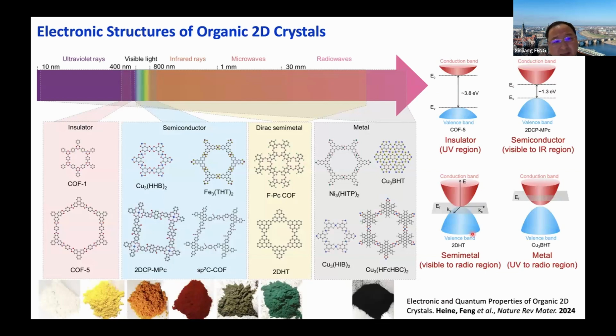In organic 2D crystals, you can find a broader range of materials, ranging from the insulators with a large band gap to the semiconductors with a well-defined band gap, Dirac semimetals, and to metallic materials, which are highly conductive zero-gap materials. So basically, you can find almost all these materials in the organic 2D crystals. It's possible to make the insulator, for example copper-based materials, with low electronic building blocks and large band gap. But it is also possible to have semiconductor materials, with the beautiful colors of these materials. And metallic states can also be made with the 2D conjugated metal organic framework, which are popular to realize the different metallic states.